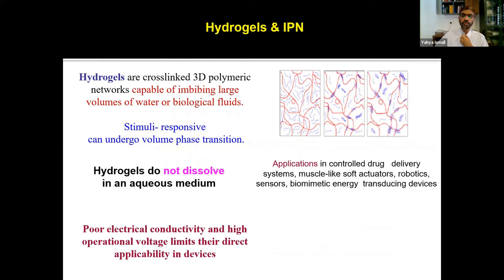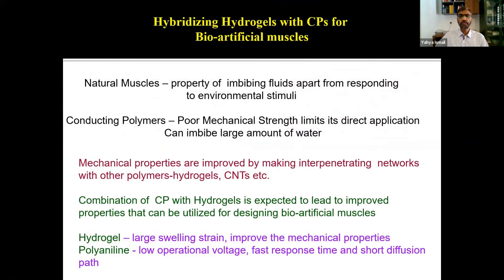I'm going to give you some experimental results on some microfibers and nanofibers from which we made bioartificial muscle fibers using conducting polymer. What we did is we took chitosan or PVA because they can produce very good mechanical stability and strength. But at the same time, the hydrogels are non-electroactive. When you hybridize it with a conducting polymer, they produce electroactivity. Then they started responding to electrical stimuli, producing linear actuation or bending actuation.